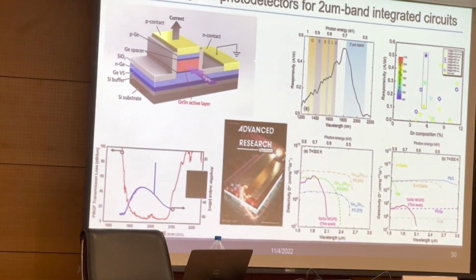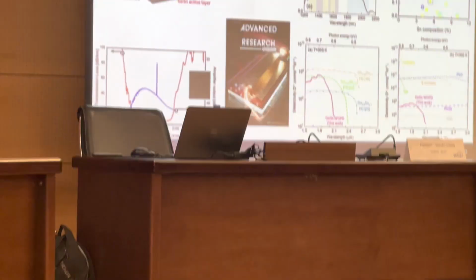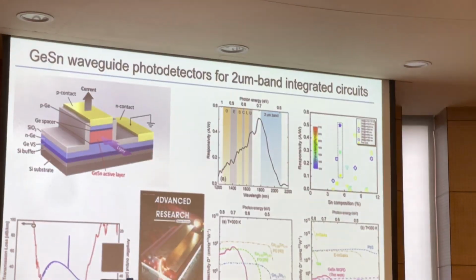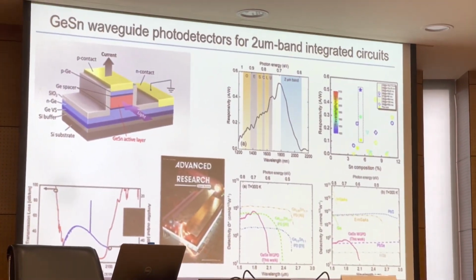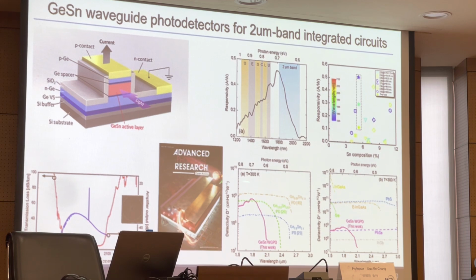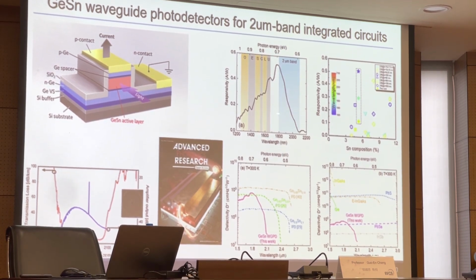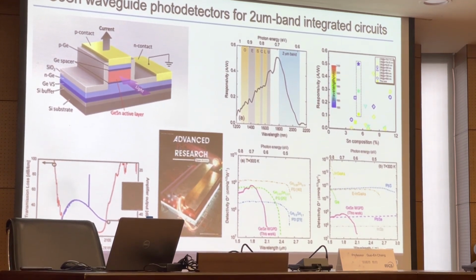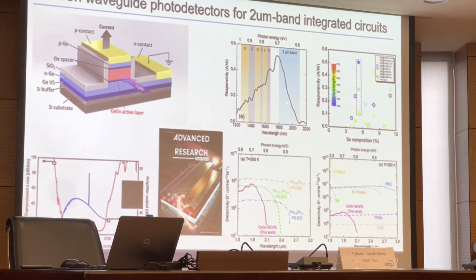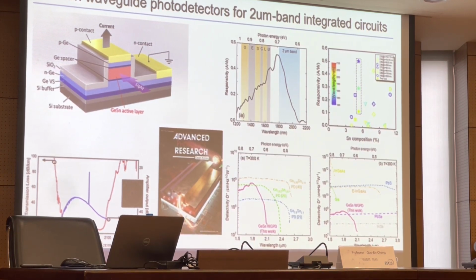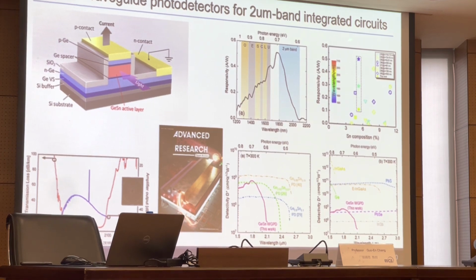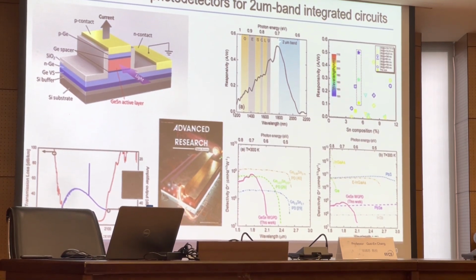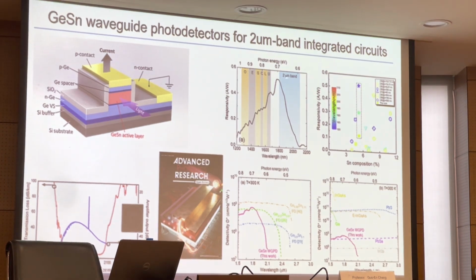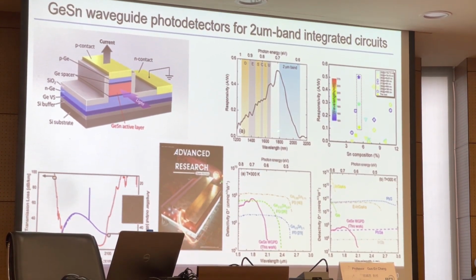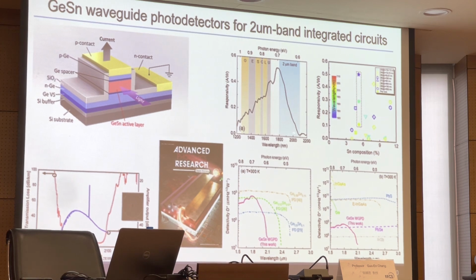This is our first work, published in 2014, and after that we also developed different generations of photodetectors. This is one work we just published this year, where we have pushed the tin content to about 6%, so the bandgap energy has been reduced to about 0.55 electron volt.